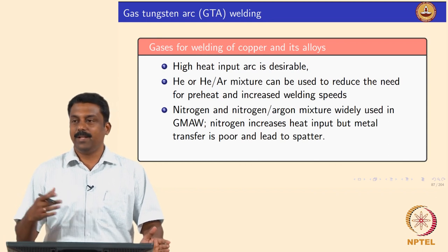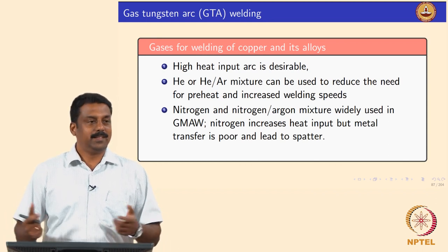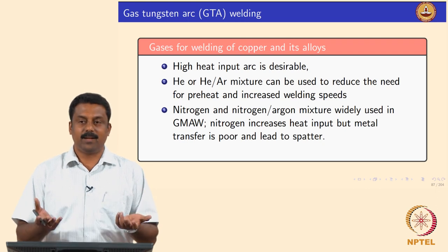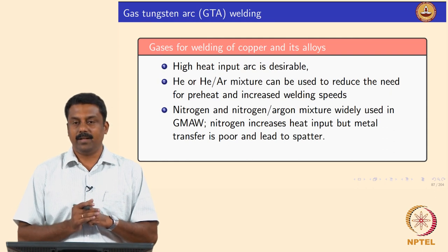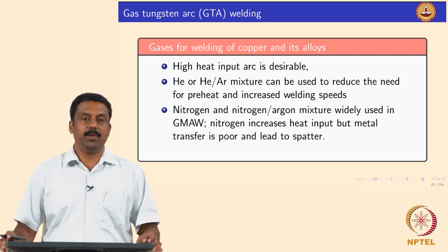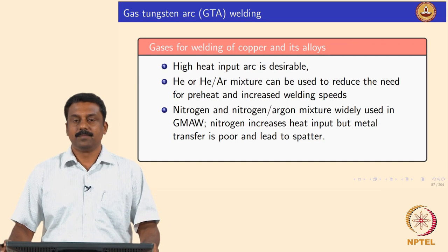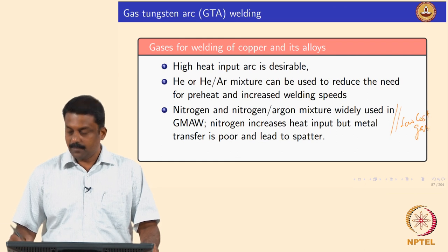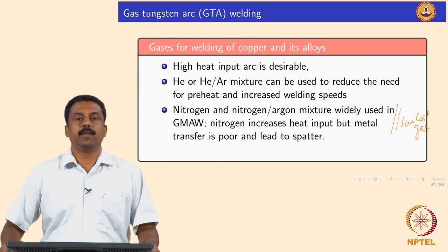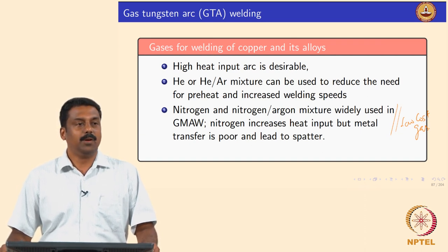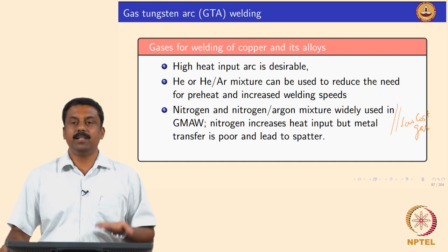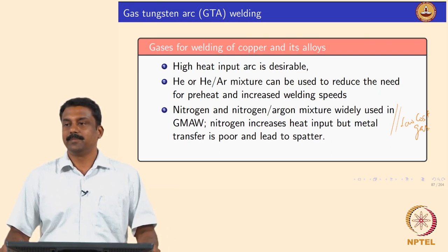For low-cost welding of copper alloys, pure nitrogen is widely used. However, because of de-dissociation, arc stability decreases - similar to carbon dioxide - and voltage increases when using diatomic nitrogen. This may lead to problems, but it can be managed if you want a low-cost gas. These considerations apply not only to arc characteristics but also to base material characteristics when choosing a shielding gas.